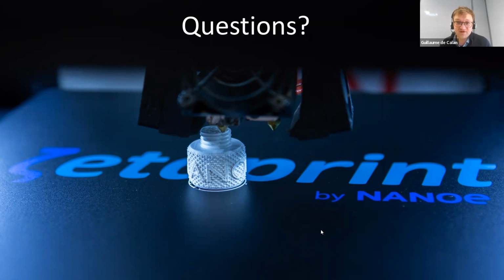Is there a phase transition in zirconia? You are right. So that's a bit for advanced users. But yes, the zirconia we're using is what we call 3Y zirconia, zirconia with 3% molar of yttria. It's a zirconia that has a phase transition toughening mechanism from tetragonal to monoclinic. So the powder itself is already mainly tetragonal. When you sinter it, it stays tetragonal, but during the life cycle, if you have some mechanical aggression, it may transition to resist to these shocks.